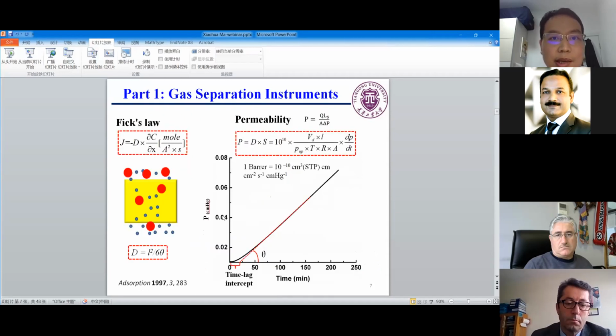And for gas separation, the permeability of flat sheet and hollow fiber membranes is based on Fick's law, and we can reach the steady state based on the downstream volume, the upstream pressure, and the steady state flow rate. We can get the permeability of the membranes, and based on the time lag, we can get the diffusion coefficient and also the solubility coefficient of the membranes. We can get a deeper insight into the properties of the membranes.